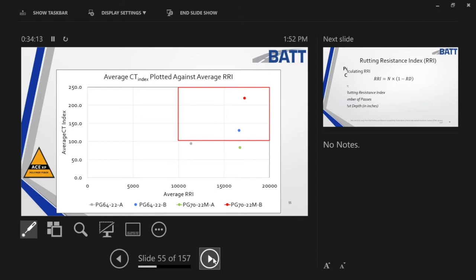And that's what you're looking at on the bottom. On the left, a higher CT is better, an Ideal CT. And so these are some values that I put together. So that red box says, I want to be in the performance zone. If I took that same 64-22 and 70-22 that I had before and looked at them by themselves, neither one ends up in that box. When I put the aramid fiber into them, both of those go into the box.